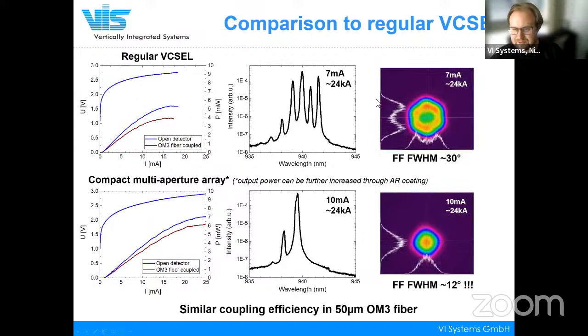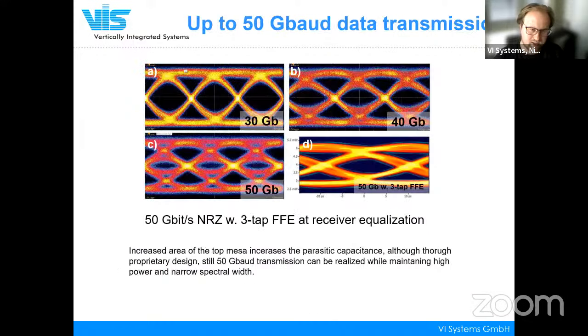And here you see the far field. So of course, the multi-mode VCSELs shows a donut-shaped far field as usual, which is not very desirable for fiber coupling, but the single mode multi-aperture chip at the same output power shows very beautiful Gaussian profile with full width half max of around 10-12 degrees. And this is what enables it to have efficient fiber coupling.